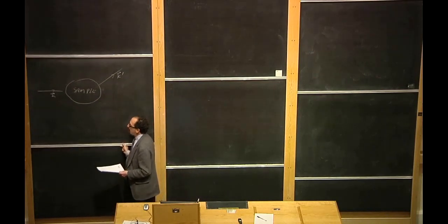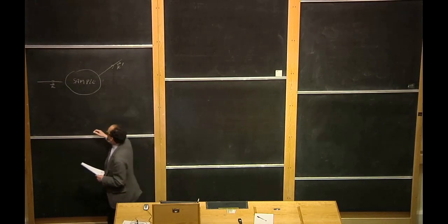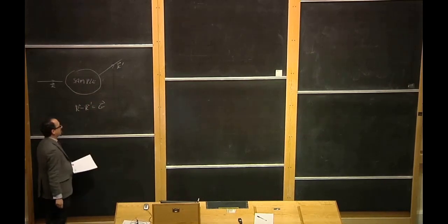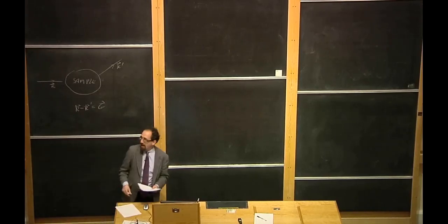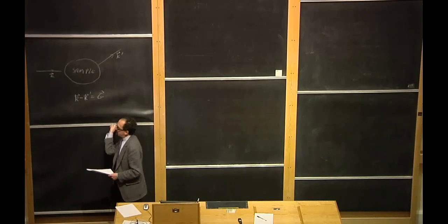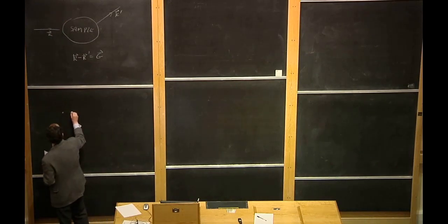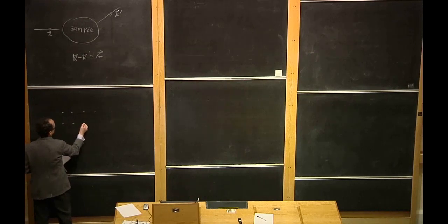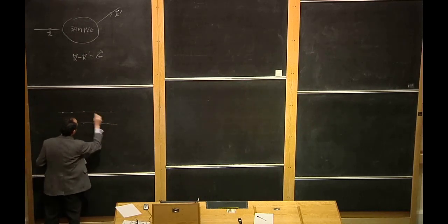One of the things we derived in the last lecture is that in order to get scattering from k to k prime, we must satisfy in a crystal the Laue condition that k minus k prime must be a reciprocal lattice vector G. At the very end of the last lecture, I claimed that this Laue condition is very similar to a condition that you have already thought about when you considered simple diffraction off of planes.